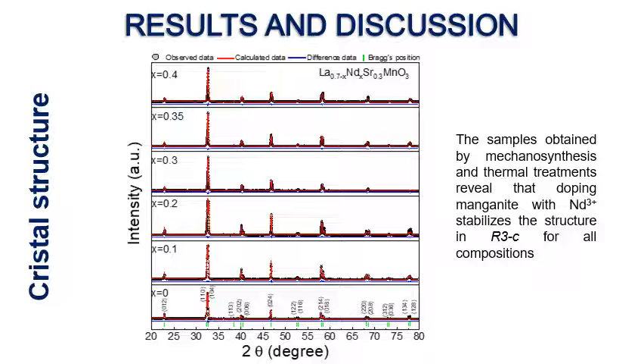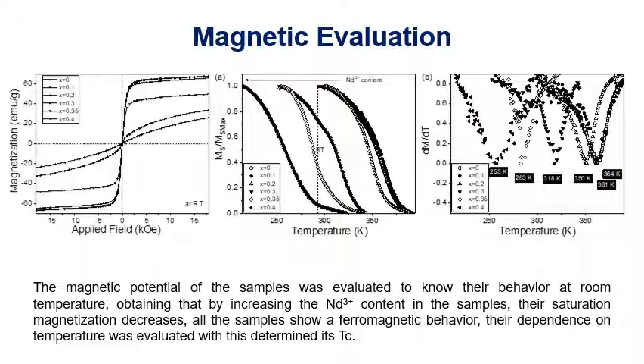The powders were synthesized by high-energy ball milling for 5 hours, assisted with heat treatment. XRD results confirm the formation of the rhombohedral structure in all samples with neodymium content. This is confirmed by Rietveld refinement, in which the bond angles and distances with the manganese ions were calculated, confirming the displacement, with which the crystal structure suffers displacement and the magnetic properties change. The samples obtained by mechanosynthesis and thermal treatment reveal that doping manganite with neodymium stabilizes the structure for all compositions.